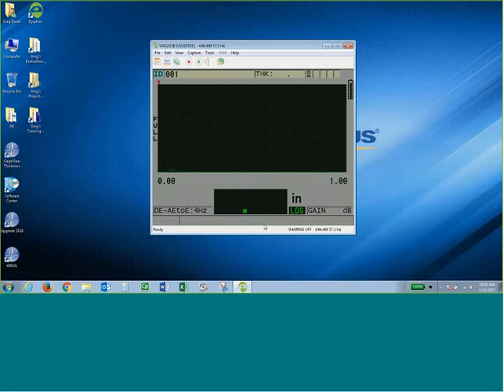So the other example is I have a sample that has clean outer edges, but the center of the sample is corroded on the back surface. So if you see here, when I couple on to the outer edge, I'm making a valid echo-to-echo measurement. But if I couple onto that middle, there's only one back wall on screen. I'm not ignoring the coating. So a through coat would kind of solve this issue. So let's see what happens when I use a through coat transducer.